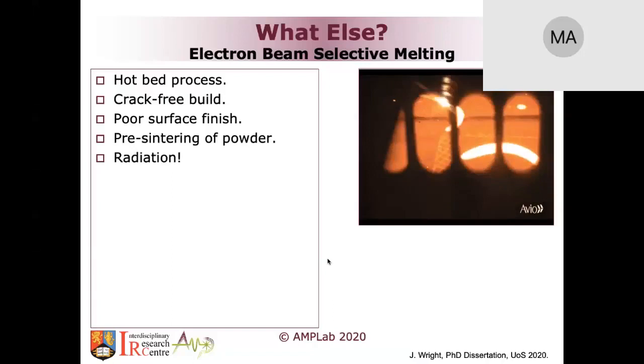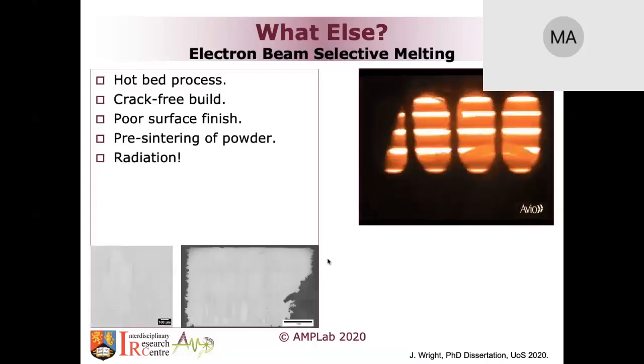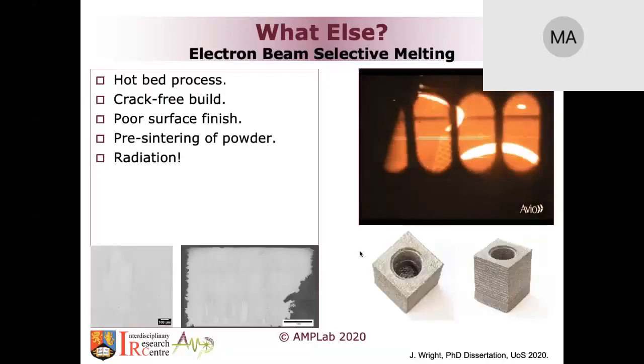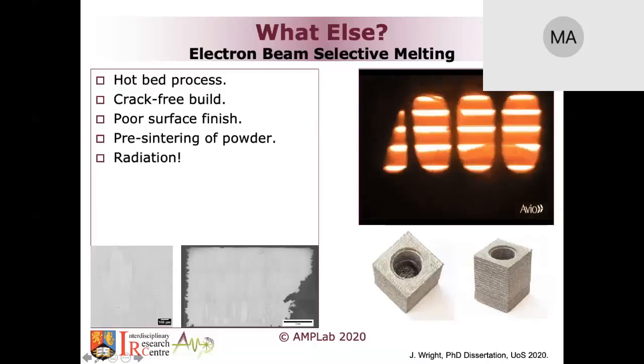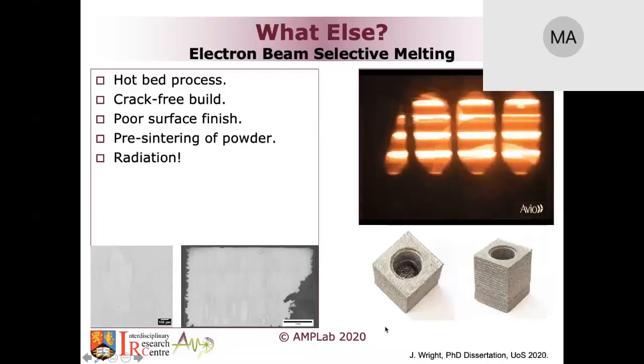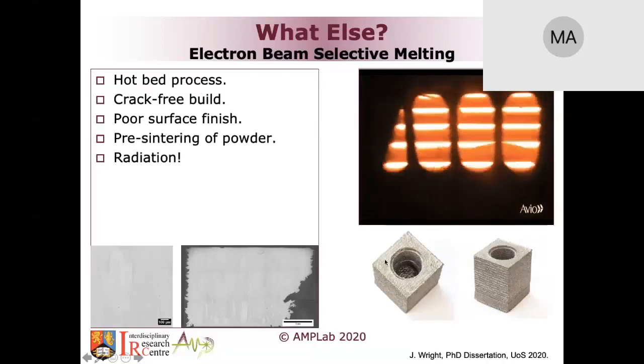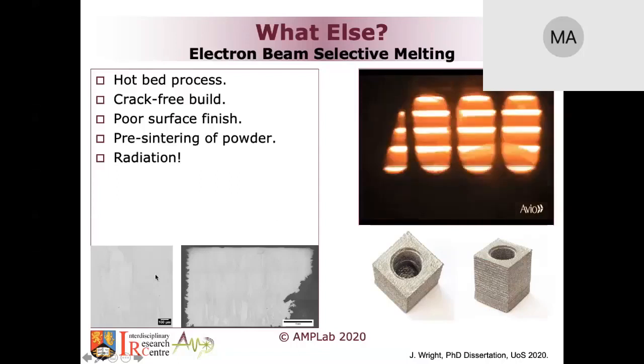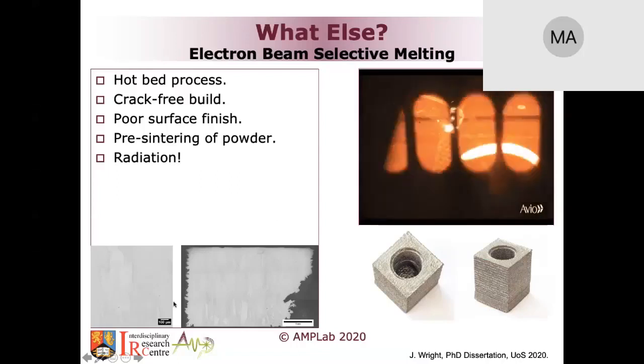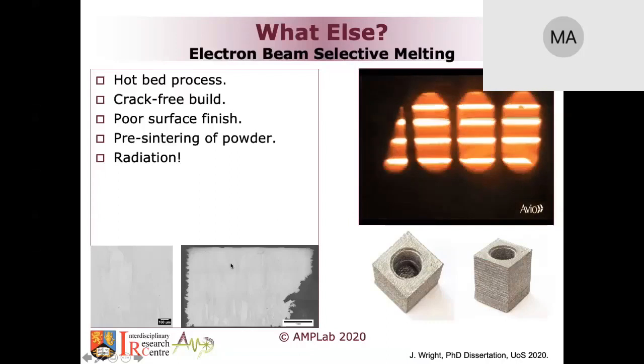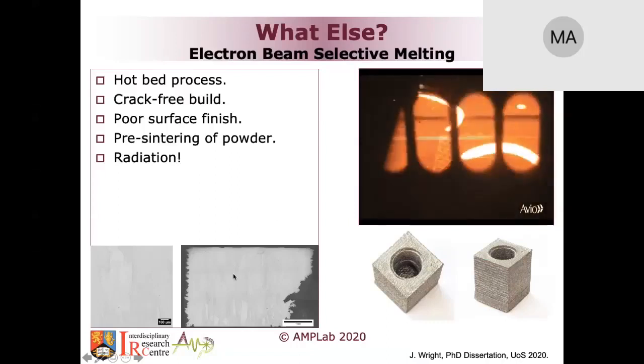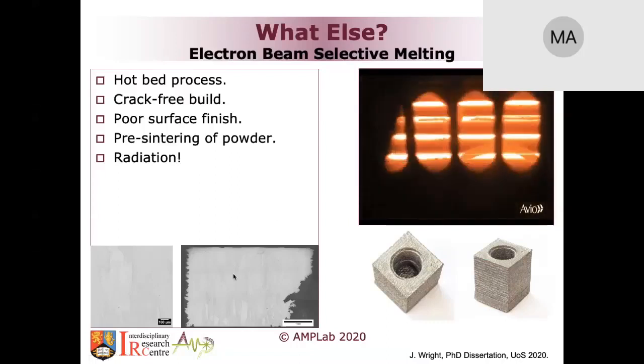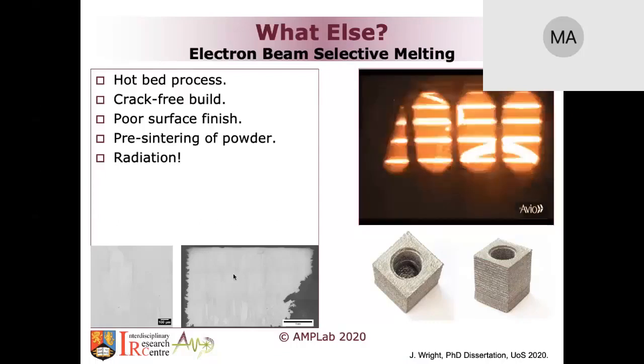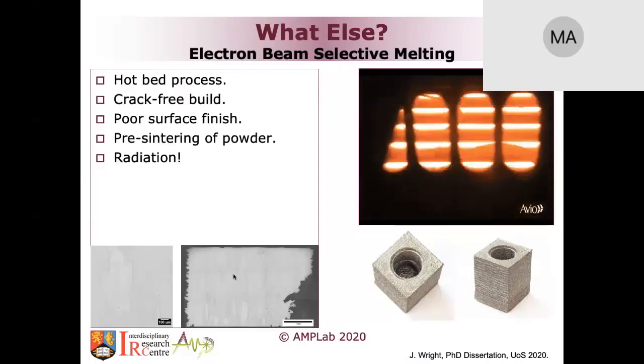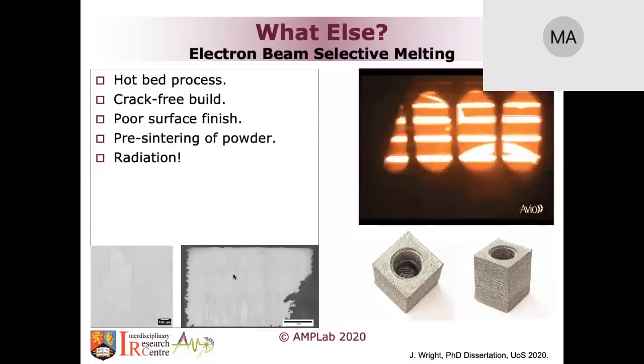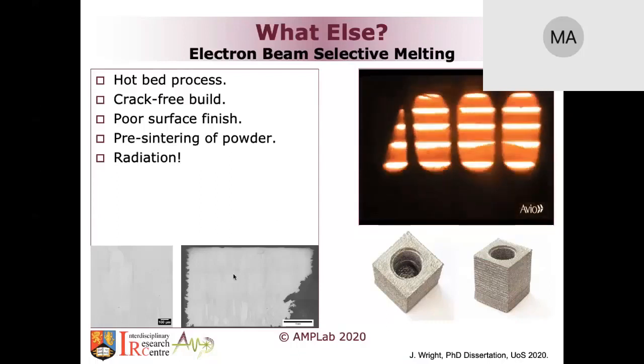There's only one study that I saw that managed to print tungsten without cracks, and that study is by Jonathan Wright from Sheffield University, who used an electron beam technique to print tungsten. As you can see, this is a section of the build he made, and there are no cracks whatsoever. The part is fully dense. The material is printed at a very high temperature in a heated bed, so you can control the cooling to a level that does not induce significant cracking. There's an in-situ stress relief.